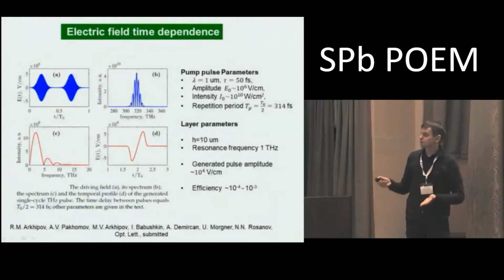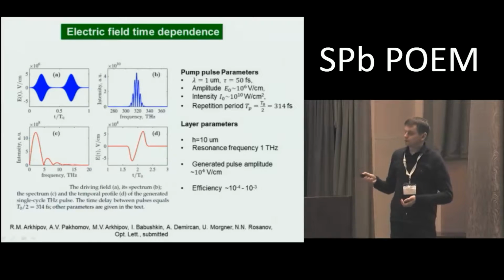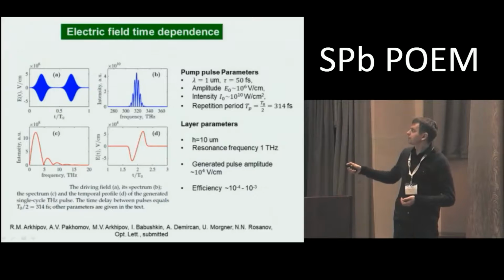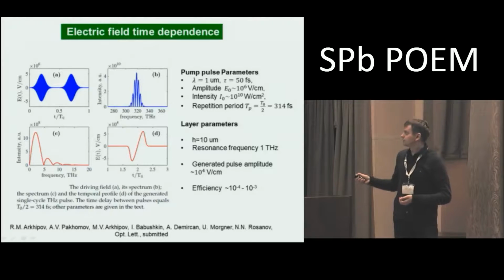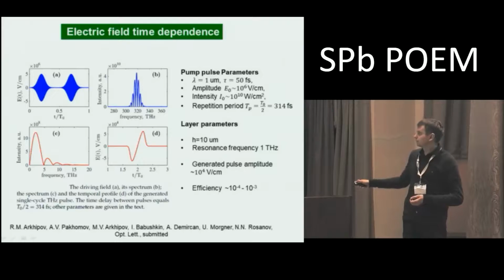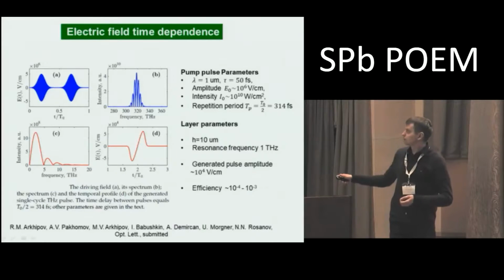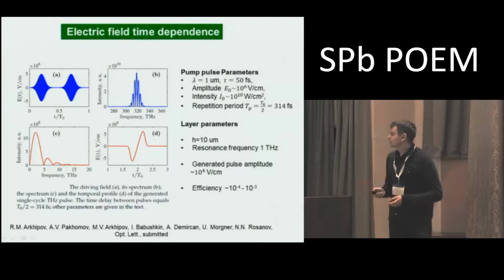So this figure illustrates this idea in detail. Here is the pumping pulse train and the pumping pulse spectrum. We consider pumping femtosecond pulses typical for a Titanium sapphire laser, at 1 micron and duration of 50 femtoseconds. And the generated reflected field is the single cycle terahertz pulse, which is illustrated in this figure. In the numerical simulations, we use a layer 10 microns thin, and the resonance frequency of the layer is 1 terahertz. The generated pulse amplitude has a value of the order of 10 to the power 4 volts per centimeter. So using this method, we can achieve an efficiency of 10 to the minus 4 to 10 to the minus 3, which is very high.